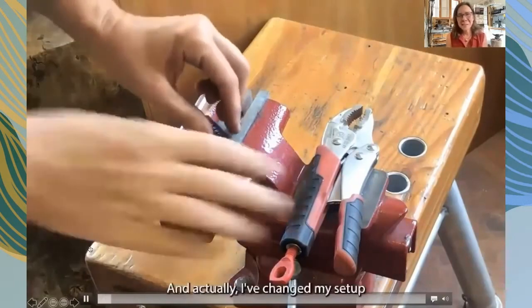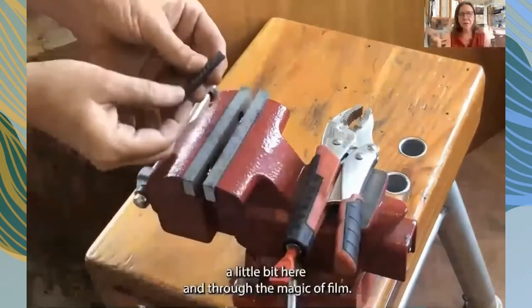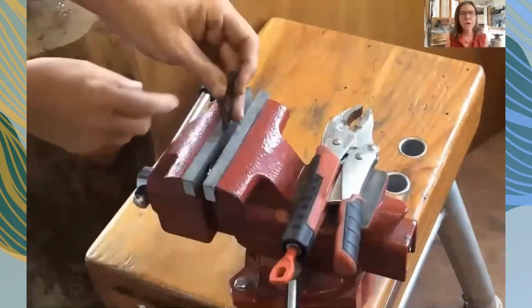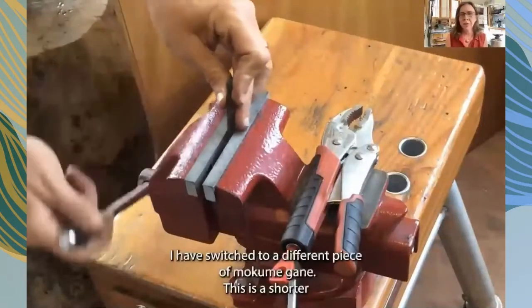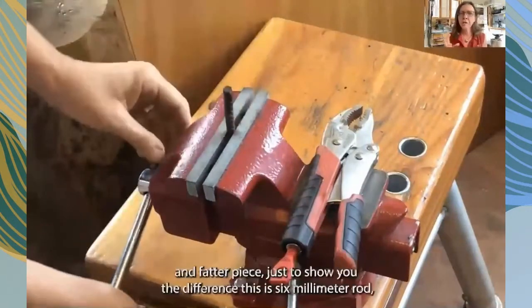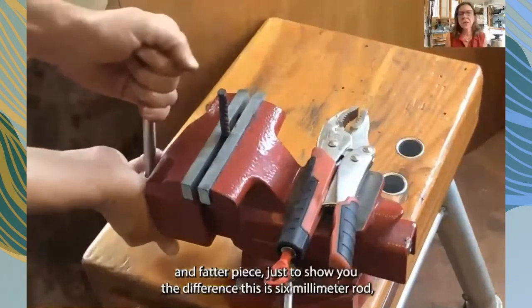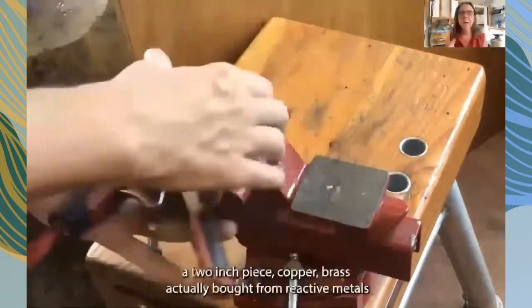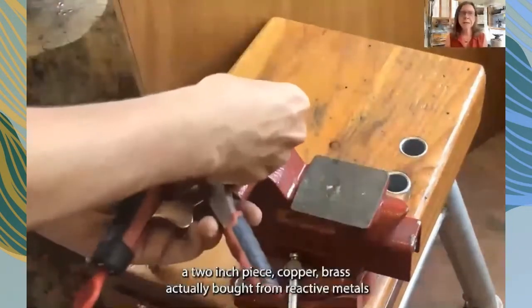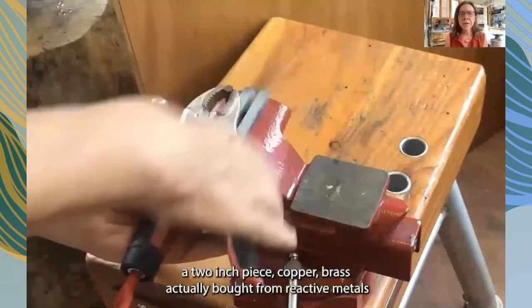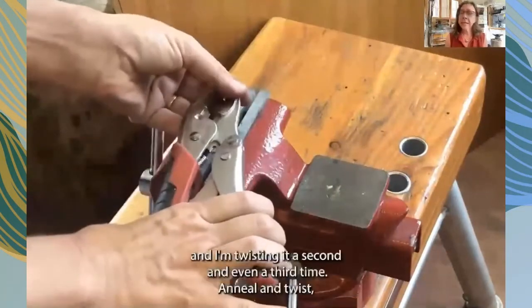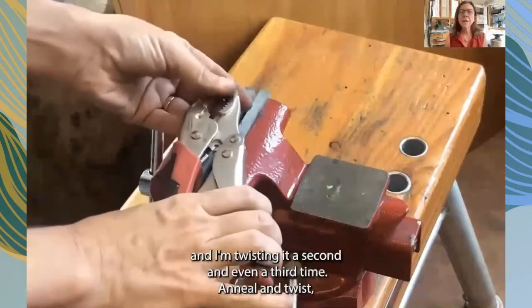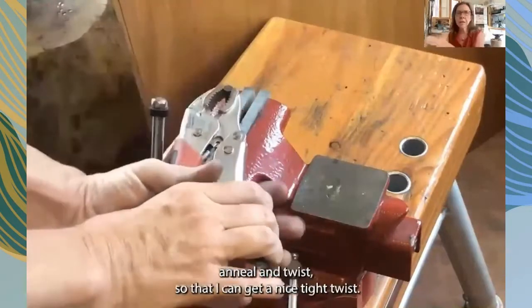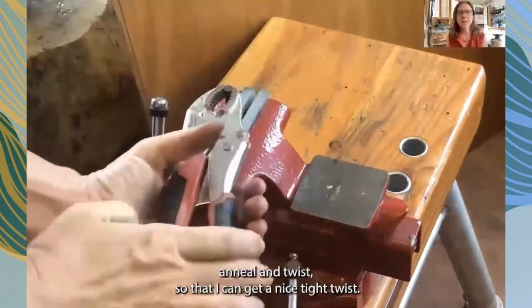And actually, I've changed my setup a little bit here. And through the magic of film, I have switched to a different piece of Mokume. This is a shorter and fatter piece, just to show you the difference. So this is 6 millimeter rod, a 2-inch piece, copper brass, actually bought from Reactive Metals. And I'm twisting it a second and even a third time, anneal, twist, so that I can get a nice tight twist.